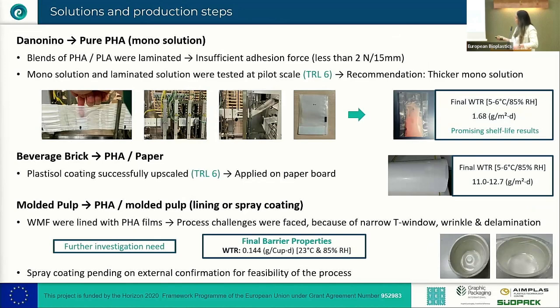I will go briefly here for the PHA solutions, because Willem already explained in detail what we did, but I would like to point out what were the challenges that we faced with the upscaling. First, as Willem already said, we have very thin films of PHA, and when we put it in the machine, we saw that the mechanical stress under high temperature for this material was too high. Then you see we have some deformations.